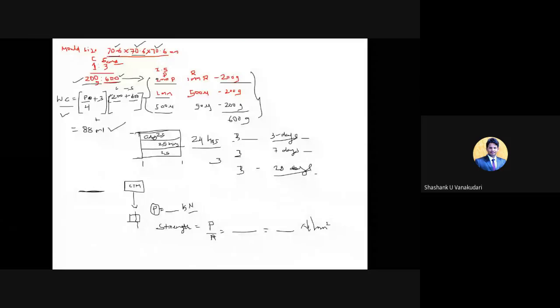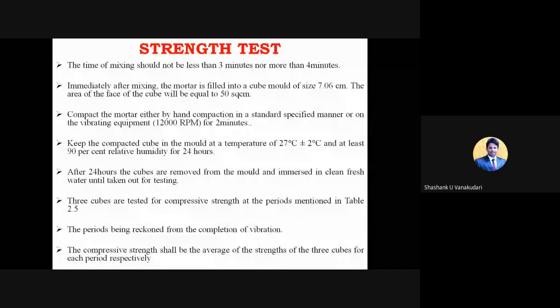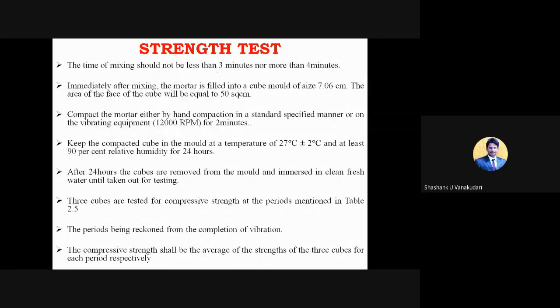in this formation, that is 2 mm passing 1 mm retained, 1 mm passing 500 microns retained, and then 500 microns. Yeah, and then the mixing time should not be less than 3 minutes, and it should not be more than 4 minutes. That condition also has to be satisfied.